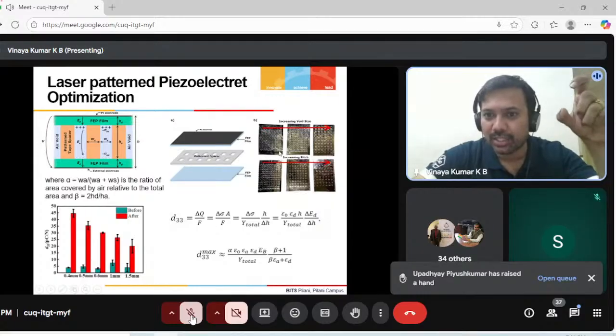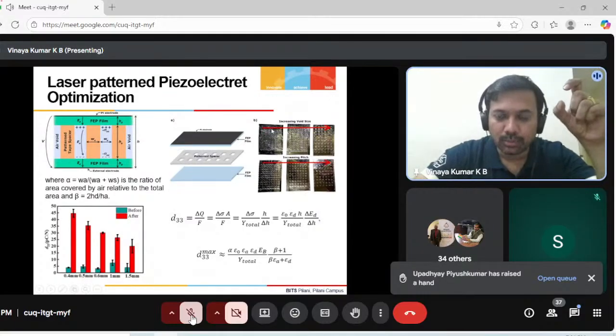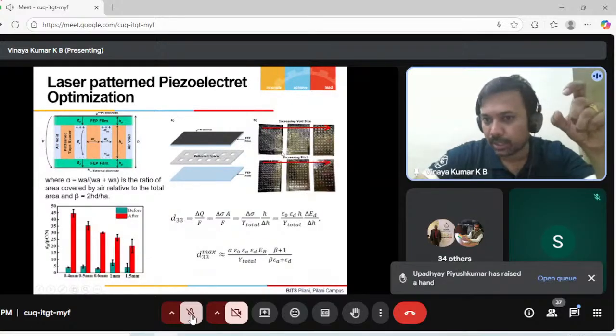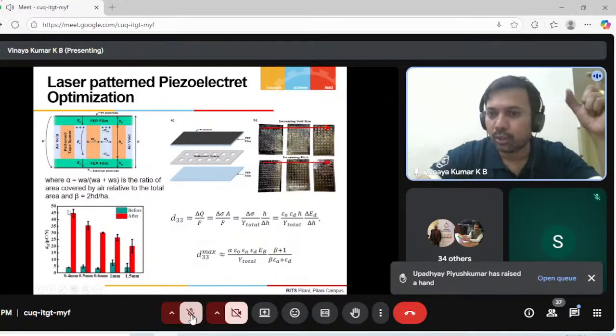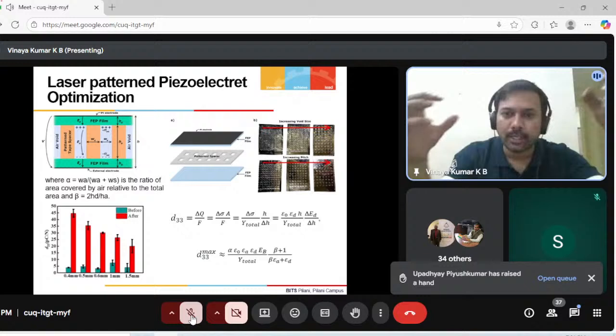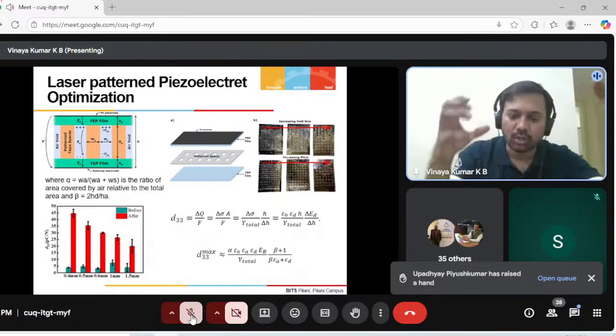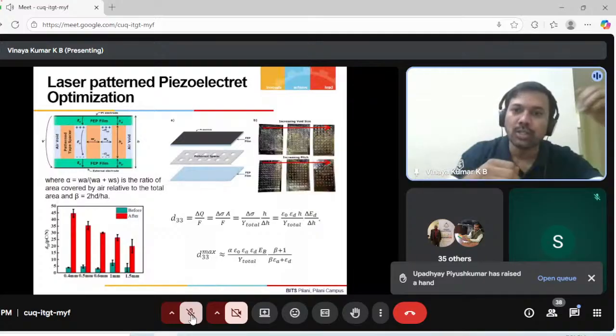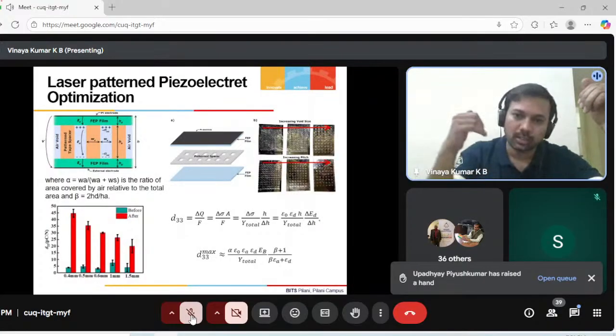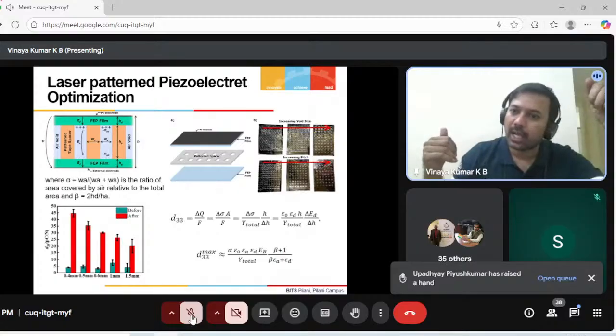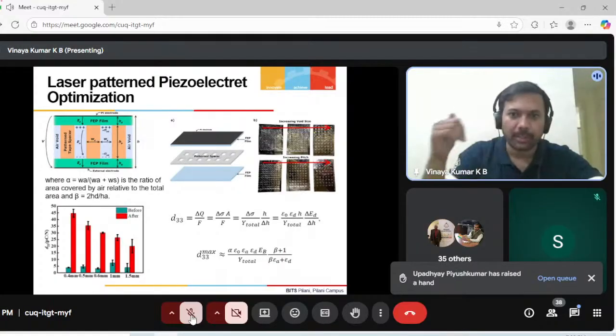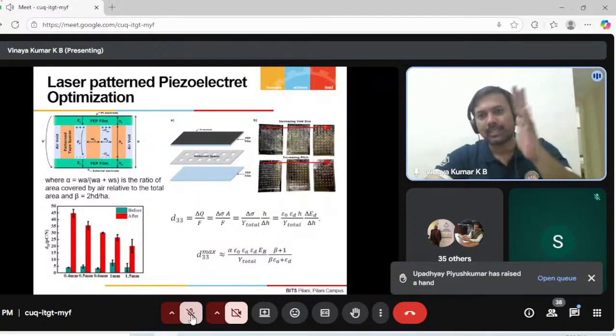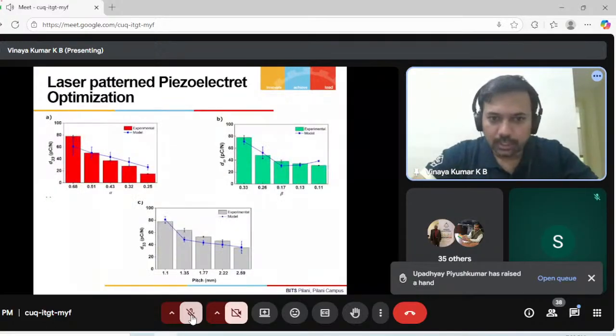The charge density stored in smaller voids in the same area of the device is much more than the charge density in this particular device. Right? With this, we are able to show that the smaller the dimension, the more sensitive the devices we get. So depending on the application, by tuning the void dimension, we are able to design the piezoelectric coefficient of the device so it can be used to detect either very sensitive pressure, or moderate pressure, or very high pressure. The same device, by tuning the fabrication method, can be made to sense different levels of pressure.